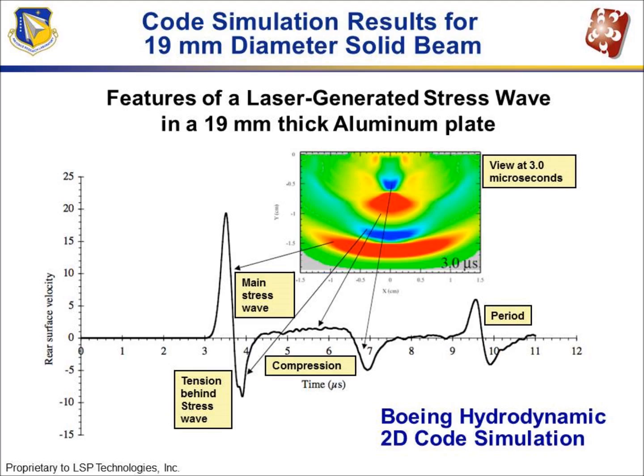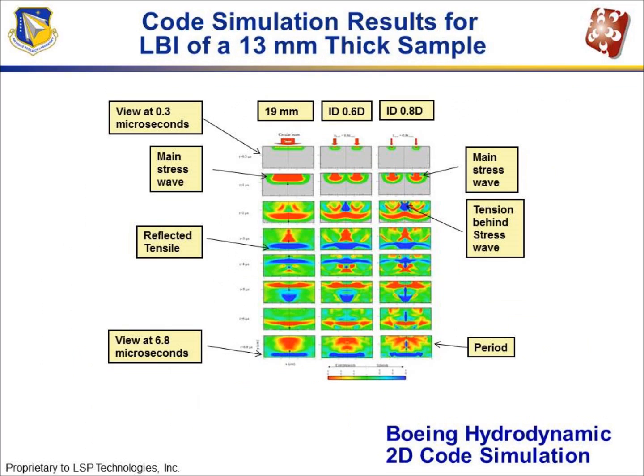Laser bond inspection creates a stress wave that can test the strength of an adhesive interface in a composite bond. The strength of the stress wave can be selected by varying the energy and pulse width of the laser beam. The strength of the reflected tensile stress wave produced can be selected to fail weak bonds while strong bonds are unaffected. I'll describe that more when we cover how we measure bond strength. LBI can be set to detect weak bonds. It is non-destructive to strong bonds.